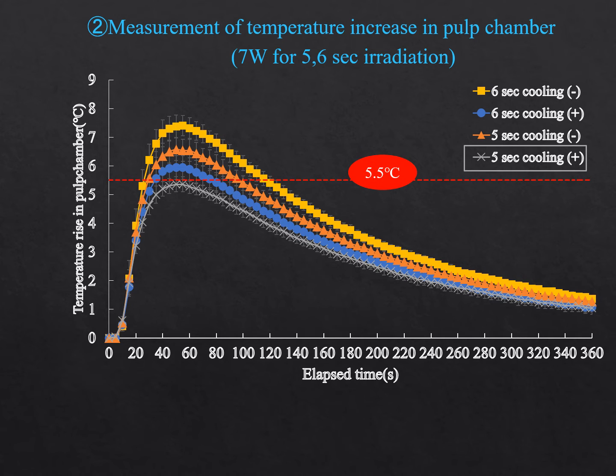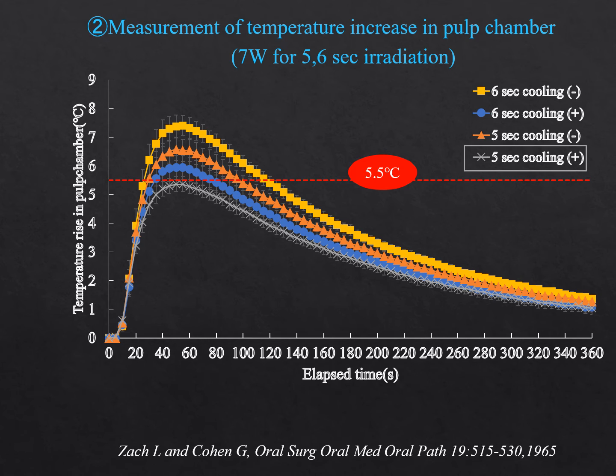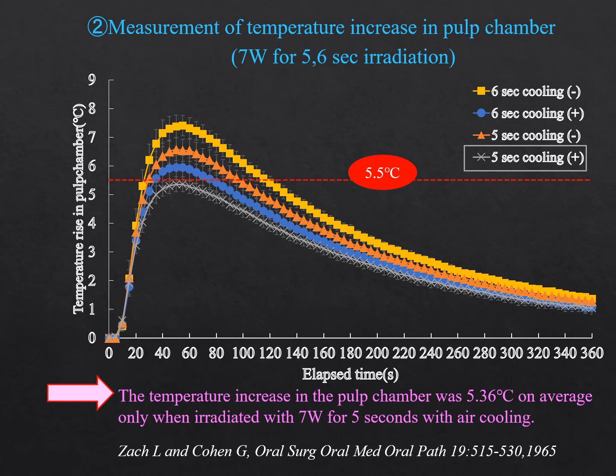Temperature increase in the pulp chamber after irradiation of 7 watts for 5 and 6 seconds was also measured. Zach and Cohen reported that a temperature increase in the pulp chamber of 5.5 degrees or higher may cause damage due to thermal degeneration of the pulp. Among the various conditions, the temperature increase in the pulp chamber was 5.36 degrees on average, only when irradiated with 7 watts for 5 seconds with air cooling. Therefore, the subsequent experiment was performed under this condition.